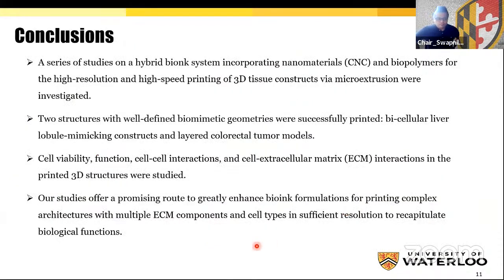To conclude, we studied a series of hybrid bioink systems incorporating nanomaterials, CNC, and biopolymers for the high-resolution and high-speed printing of 3D tissue constructs via microextrusion. We found that the CNC, with proven biocompatibility, played a vital role in improving bioink's rheological and mechanical properties. Two structures with well-defined biomimetic geometries were successfully printed, including bicellular liver lobule mimicking constructs and layered colorectal tumor models. Cell viability, function, cell-to-cell interactions, and cell-to-ECM interactions in the printed 3D structures were studied as well. Overall, our studies offer a promising route to greatly enhance bioink formulations for printing complex architectures with multiple ECM components and cell types in sufficient resolution to recapitulate biological functions.